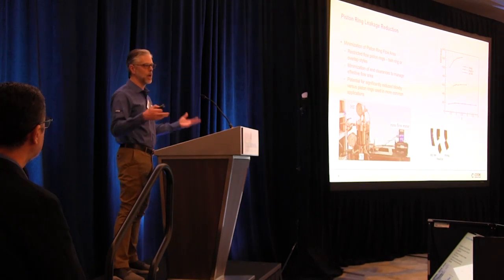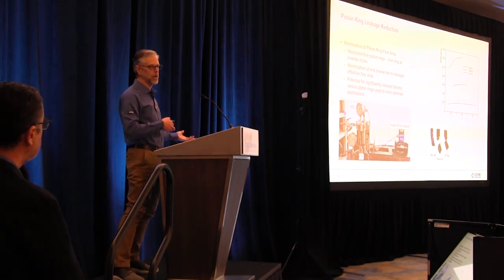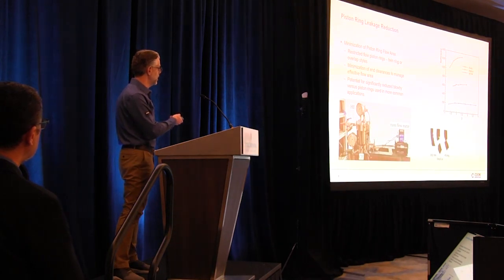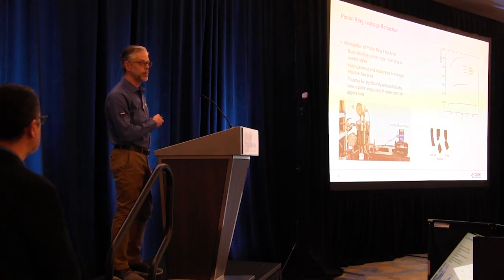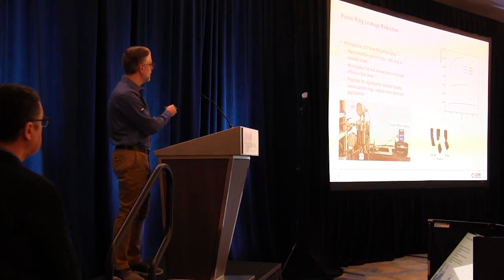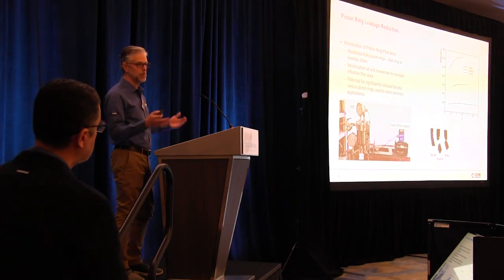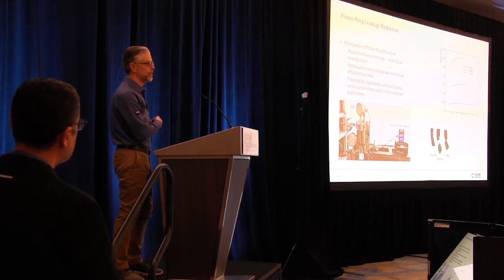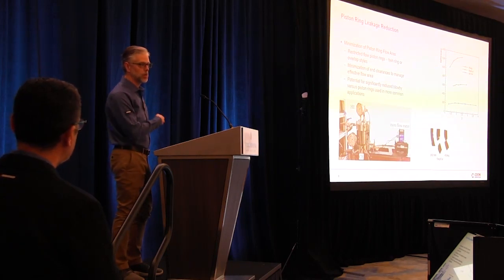So for example, if you look at just a typical angle cut piston ring that you would have in a natural gas compressor, at different compression ratios here, you get a high degree of blow-by past your piston rings. And then say you take that down to more of a restrictive type step cut, lap joint, whatever you would call that, you can cut that leakage about in half. But that's still, for hydrogen, a very high leak rate.